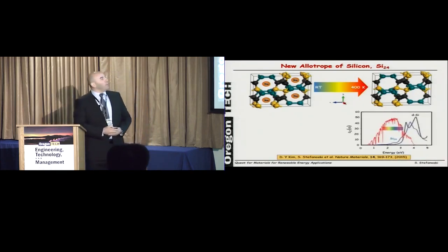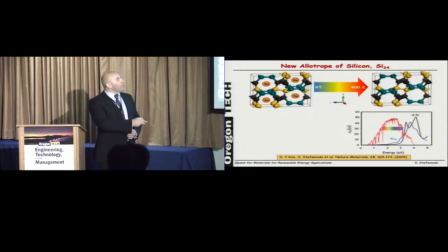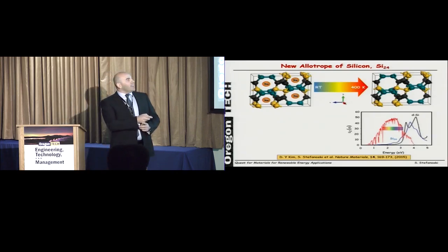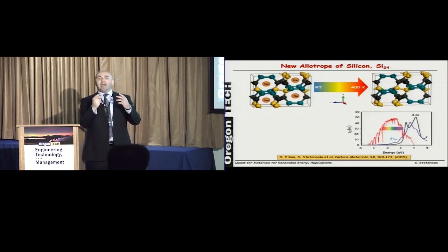Now, what is important about this material? Well, let's take a look at the absorption property as a function of energy, which we measured in a laboratory. You can see that in the visible range of the spectrum, this material has higher efficiency than conventional silicon. Another important aspect of this material is that it's a quasi-direct band gap material.